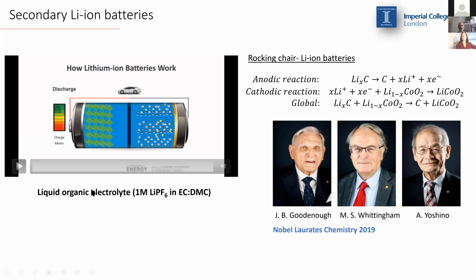Both electrodes are separated by a liquid organic electrolyte. This one in particular is typically lithium hexafluorophosphate in ethylene carbonate and dimethyl carbonate. And also there is a separator that avoids physical contact between both electrodes and therefore avoids the short circuit of the cell. Although all the portable electronics that we have nowadays are possible thanks to secondary lithium-ion batteries, they still have a lot of limitations. And most of them come from this liquid organic electrolyte that we are using.